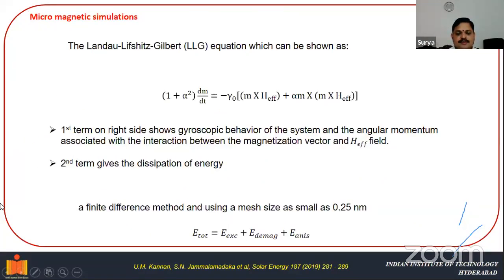Okay. So what we have done is we have done two different simulations, micromagnetic simulations. In addition to the experimental results that we have obtained, we also wanted to prove the kind of effect that we have obtained using the simulations or theoretical models like micromagnetic simulations. These micromagnetic simulations basically work on the Landau-Lifshitz-Gilbert equation. This is the equation that is given. The first term on the right hand side shows the gyromagnetic behavior of the system and the angular momentum associated with the interaction between the magnetization vector and H effective field. The second term actually gives the dissipation of the energy.